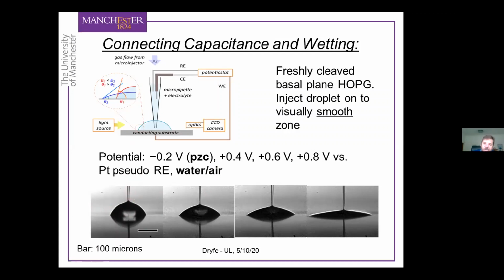injected from. And if we use our basal plane graphite as a working electrode, and we have both a reference and a counter electrode inside the pipette, then we can obviously apply a potential to that graphite, and we can measure the contact angle, which is the initial value for the uncharged surface is about 64 or so degrees, plus or minus 2 perhaps degrees. We can measure the change in contact angle as we apply a potential to that graphite surface. And you can see that you get a nice classical electro-wetting effect. The contact angle changes from the initial value of 64 degrees or something like that, down to about 10 degrees at quite low voltages.